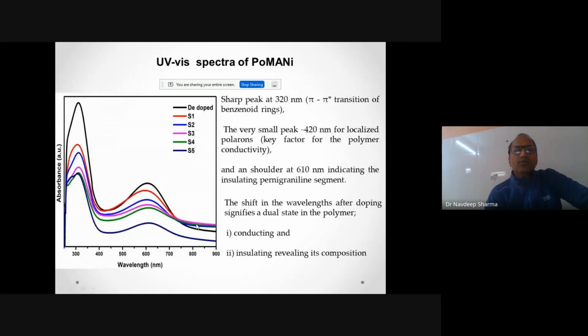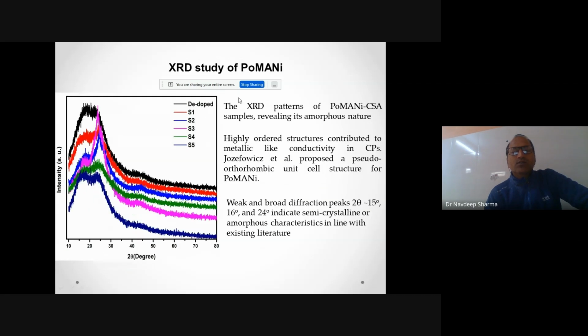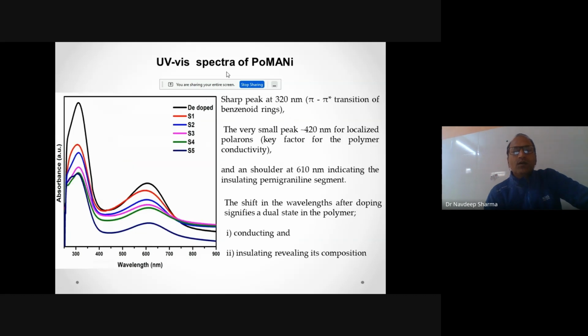And the UV-visible spectra of poly(ortho-methyl aniline) for the de-doped and other samples S1, S2, S3, S4 and S5. Actually, these S1 to S5 samples refer to the dopant to monomer concentration. We increased the concentration of dopant with respect to monomer for samples S1, S2, S3, S4 and S5 with the ratio 1, 2, 3, 4 and 5.